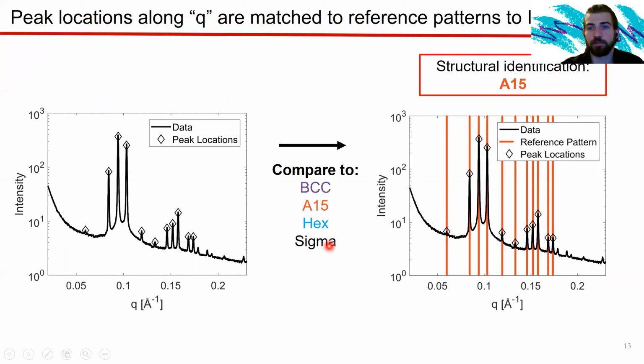And we can just compare the lines, we can slide them around, and we can use MATLAB to get a match for which phases are in each snapshot. And over here, you can see we have a nice Frank-Kasper A15 phase that we saw during the experiments. And the first 11 peaks match great, and you can actually match these 2 to the references.